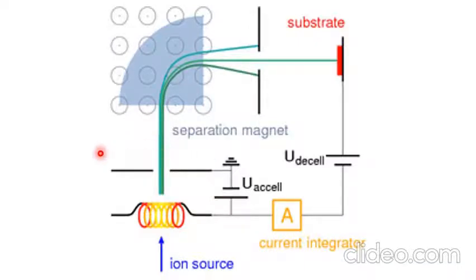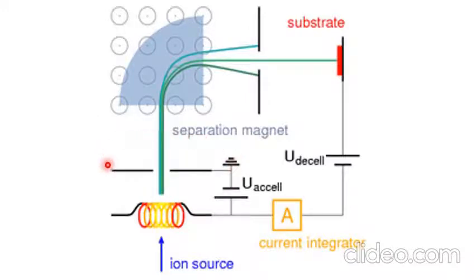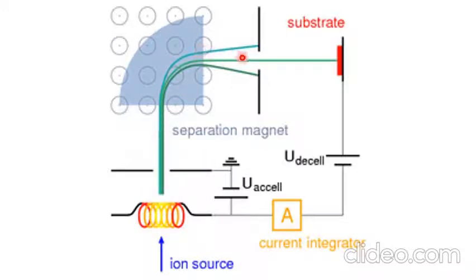In the case of a high energy accelerator, the accelerated energy is around 200 kilo electron volt to 10 mega electron volt. These high energy accelerators are used in specified applications because they give too much energy to the ions. With these high energy accelerators, ions at a density of around 10 to the power 16 per centimeter square are implanted onto the surface of the substrate.